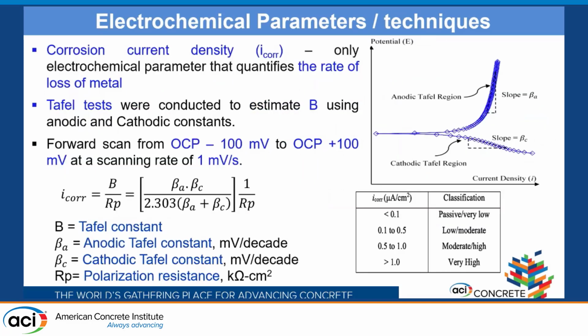Thirdly, the most critical parameter is corrosion current density. This is named as I-corr here. So I-corr is obtained as the ratio of B over Rp. What is B? B is the Tafel constant, which is derived from the anodic and cathodic constants, plugging in the values here. However, to derive the Tafel plot, we have to forward scan or polarize the system from OCP, that is open circuit potential, minus 100 millivolts to plus 100 millivolts at a scan rate of 1 millivolt per second.